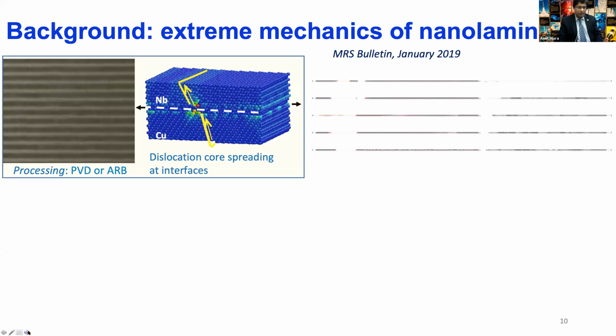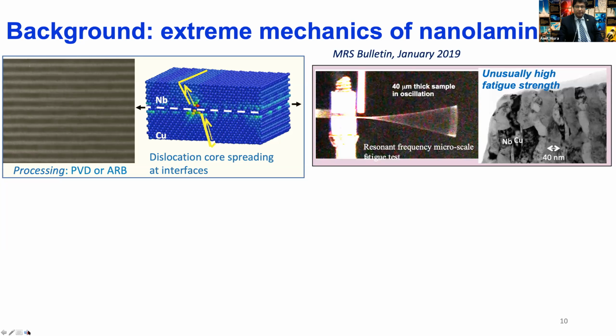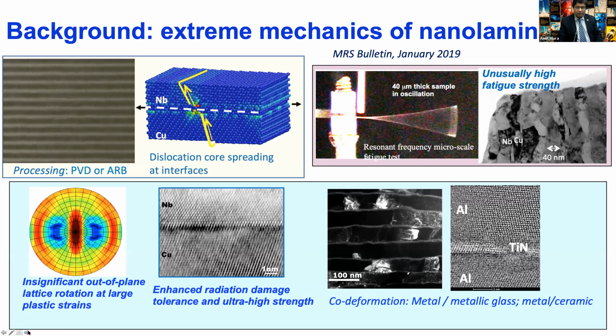And going beyond the high strength, there have been many other properties that have been discovered by virtue of these interface boundaries. You can also suppress dislocation cell structure formation and obtain high fatigue strength. These boundaries can soak up point defects. They can attract, absorb, and annihilate point defects, resulting in materials that are resistant to radiation damage.